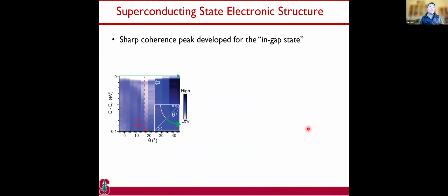Okay. So here I'm showing you data. That's a sort of raw image of the data. And you can see as I move from here, the nodal direction, to the antinodal direction, the spectra move to higher and higher energy, and reach a maximum at the anti-ferromagnetic hotspot. Okay, and this is the pseudogap phenomenon, as you will see. That's where the gap is.